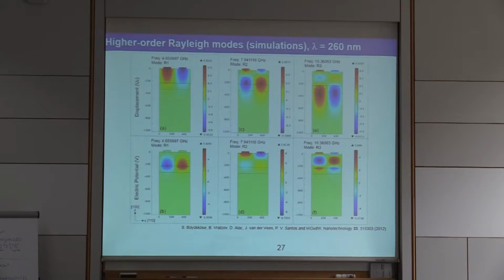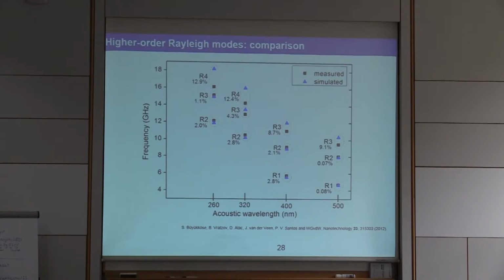Here is also the highest, this is 260 nanometers, so the smallest wavelength. There you can also see them. Okay, this is the comparison between the calculated or the simulated values and the measured ones. So here you see frequency, the acoustic wavelength, and these numbers correspond with the fundamental, first, second, or third mode Rayleigh modes. And you see, normally speaking, the agreement between simulated and observed values is very reasonable.